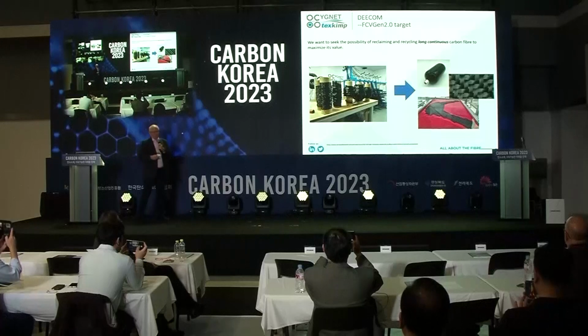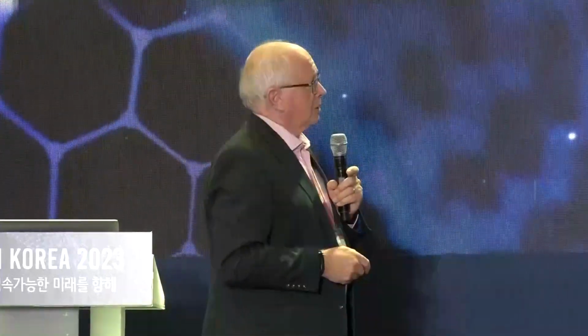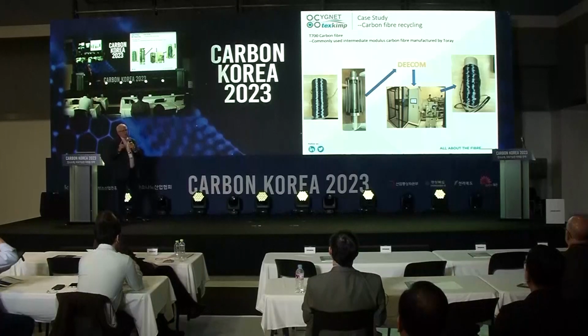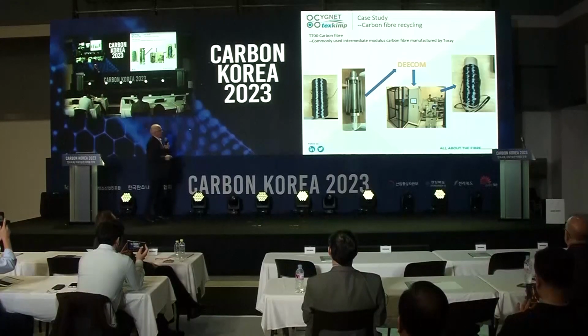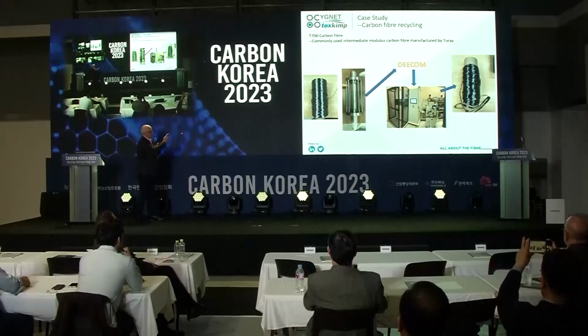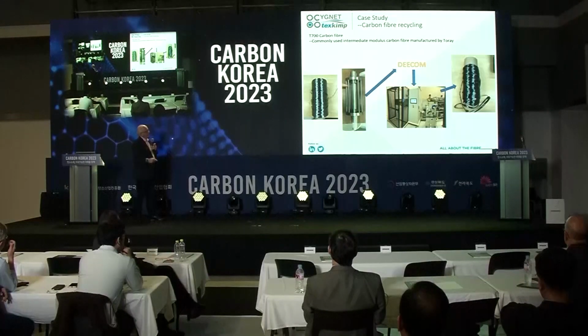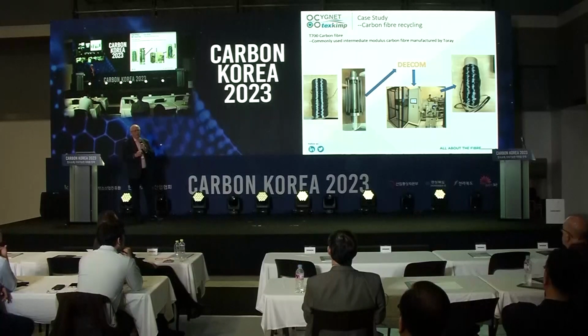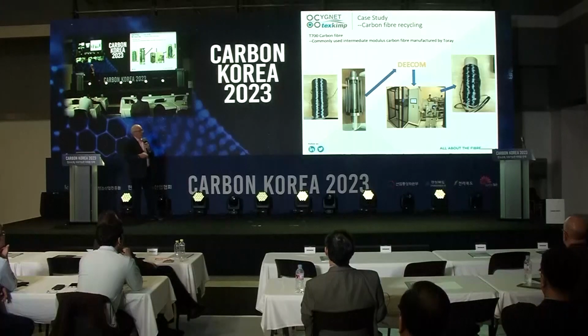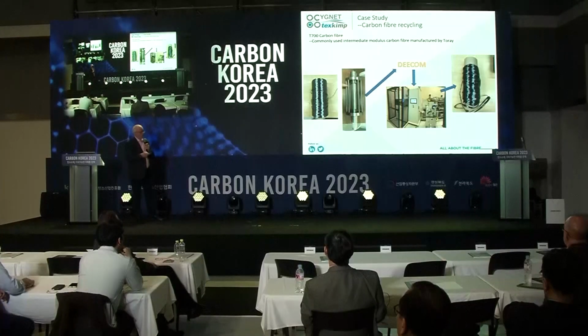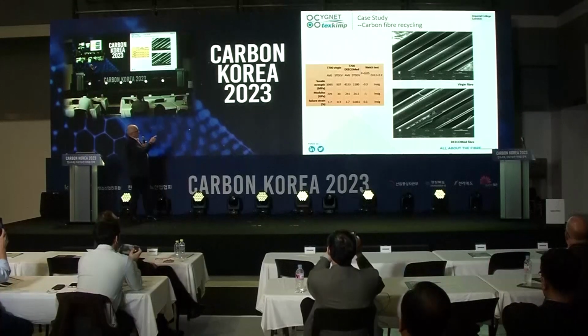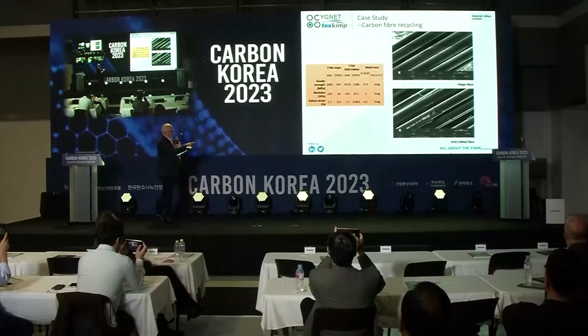So we did a test to see if we could actually do this, which was the recovery of carbon fiber from a hydrogen vessel to see if we could get the long fibers back out of it for reuse. So our first step was to take a known item, in this case a bobbin of T700. We put it through the system and we recovered it on the right-hand side there, and we measured just to see if we saw any degradation of the material at all, both materially and visually. And we found actually there was absolutely no difference to material one to the other after it had been through the process. So you can see on the top there is virgin fiber, on the bottom is some decommed fiber, as we call it.